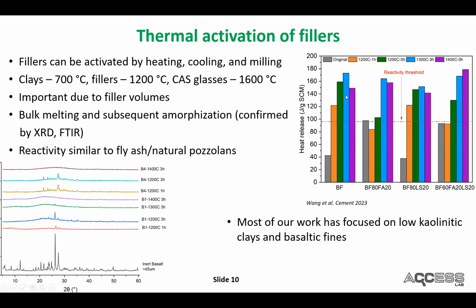So what is happening? Well, at high enough temperatures, you get bulk melting and subsequent amorphization. We've confirmed this using XRD and FTIR, and you can see in the XRD curves that beyond a certain point, all the peaks vanish. FTIR also shows peak broadening. And the reactivity is generally similar to fly ash or natural pozzolans.